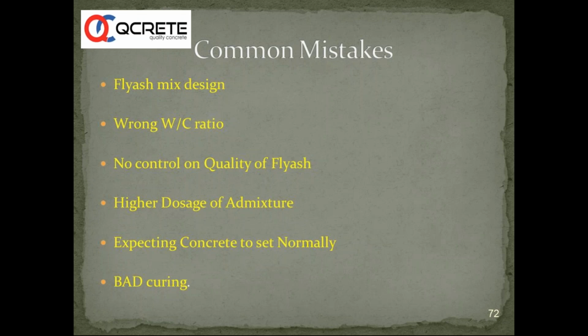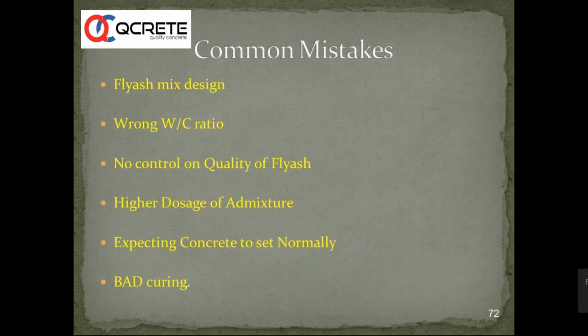So having gone through the benefits, having gone through some of the examples, some of the experiences that we have got, what mistakes happen actually? What mistakes do we make when we are talking about fly ash concrete? When we are doing fly ash concrete, let's say we are having a 320 kg OPC mix. We cannot take a 320 kg mix and directly replace with fly ash to get the same strength.